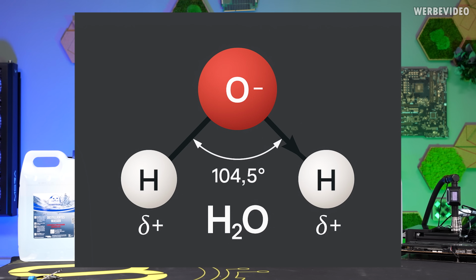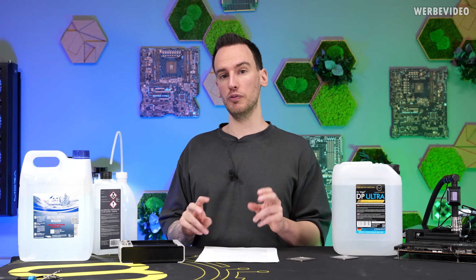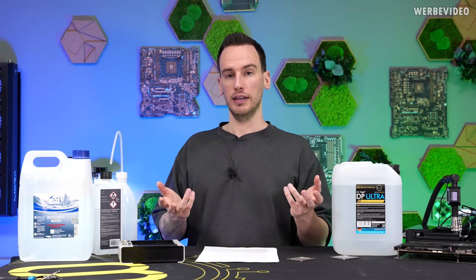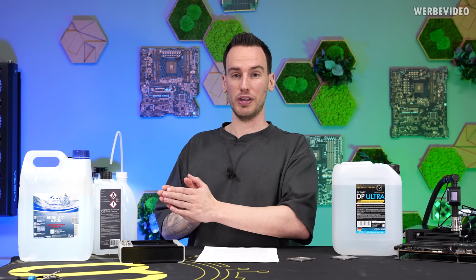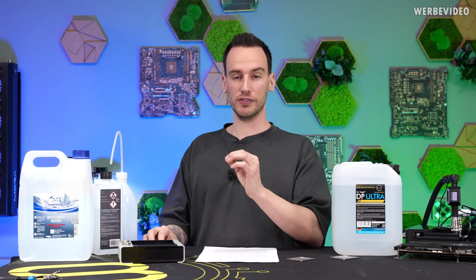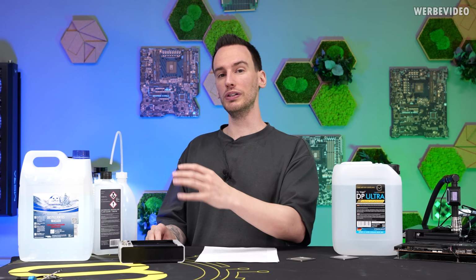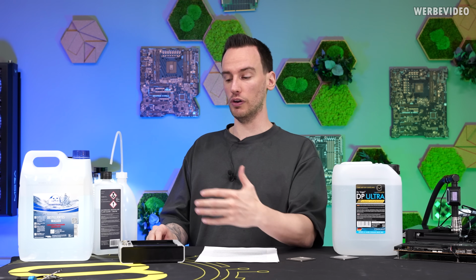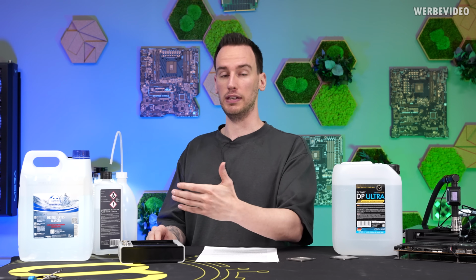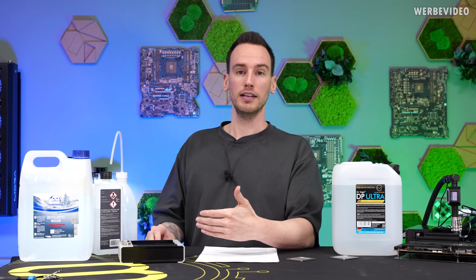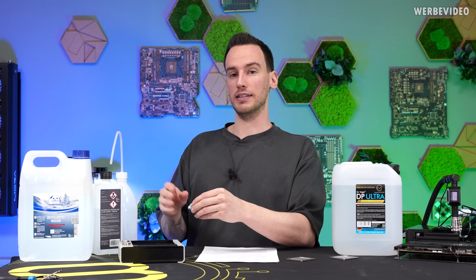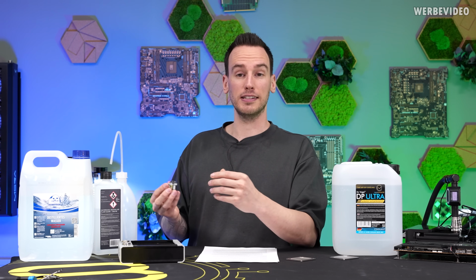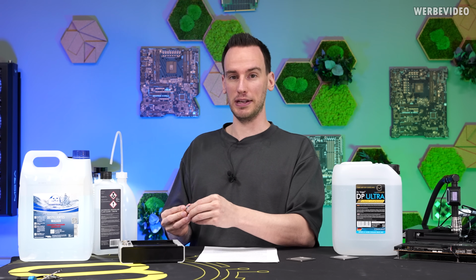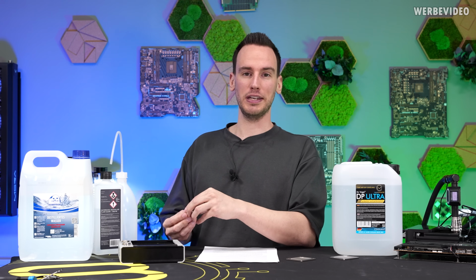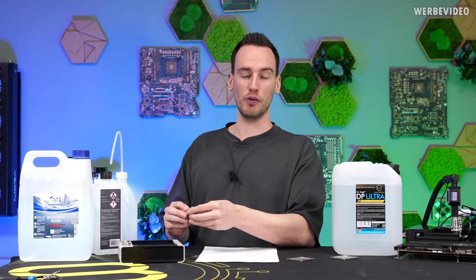And we just talked about how many different types of metals we have inside our cooling loop, potentially, even if we call it a copper type of loop. And if you fill it with distilled water without any kind of additives, it will just be a matter of seconds, within minutes at most, that the distilled water will absorb ions out of your loop from all the different materials, be it the copper, the zinc, the tin, the lead, whatever. It's not that you can run this for, let's say, a day and not worry. It happens within minutes. And the result of this, we can now see if we take our corrosion test out of the oven.